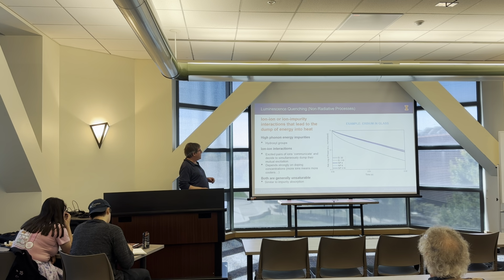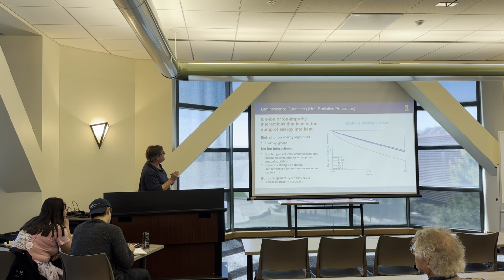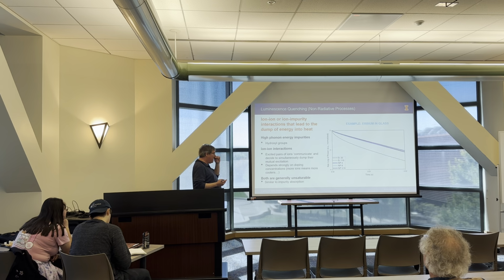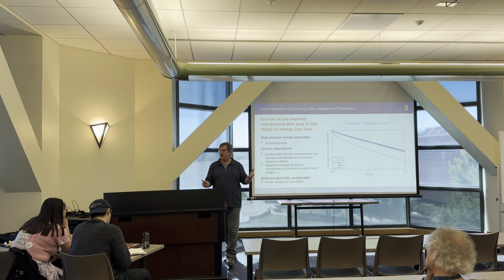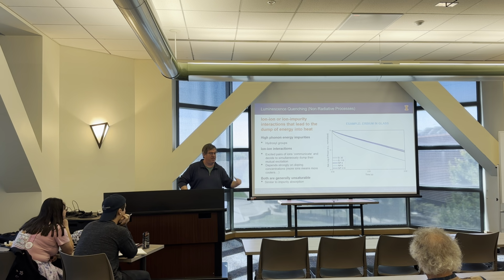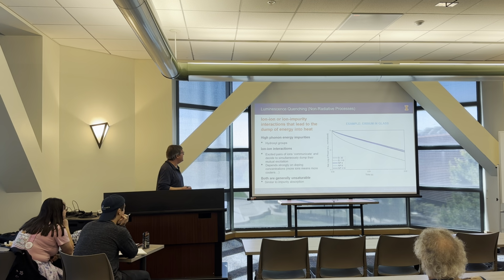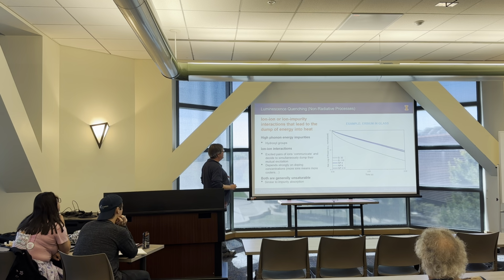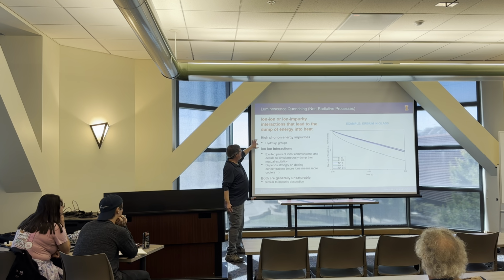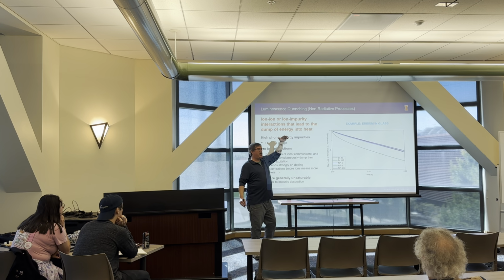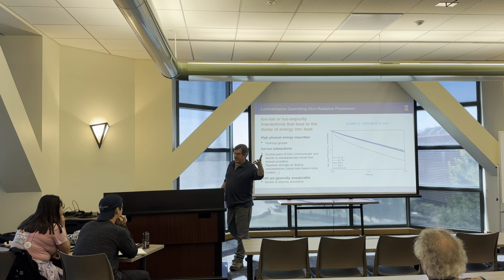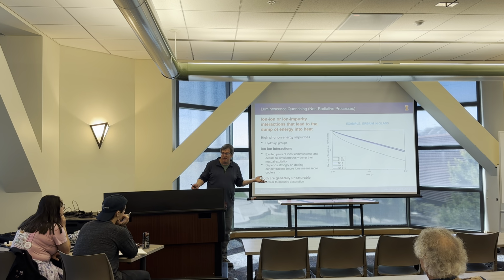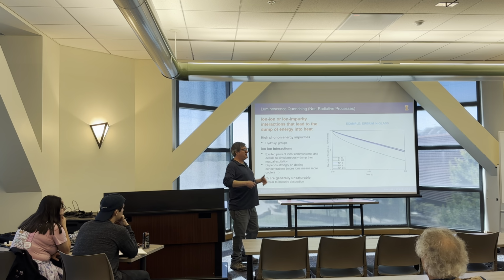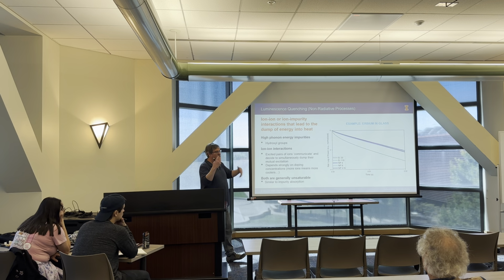Another limitation is luminescence quenching. There are processes where I excite a rare earth and it decides not to make light but to make heat. Some of these come in the form of high phonon energy impurities. De-excitation from an upper level: this is one of the reasons why ytterbium is so nice, is that the energy level difference is about 10,000 inverse centimeters. For most materials, that's greater than 10 phonons, and the probability of a phonon dump is very low in ytterbium. So that's another reason why it's magical.